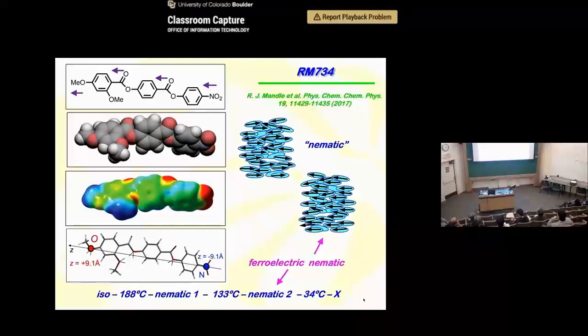Okay, so in this paper, the phase sequence for this molecule was reported as isotropic, and then it went to the nematic 1 phase, and then at 133 degrees, a second nematic phase. So the report was we have a new liquid crystal with 2 nematics. There was only supposed to be 1 nematic, but they found 2 nematics. And so that attracted our interest. And so the nematic phase is sort of sketched here.